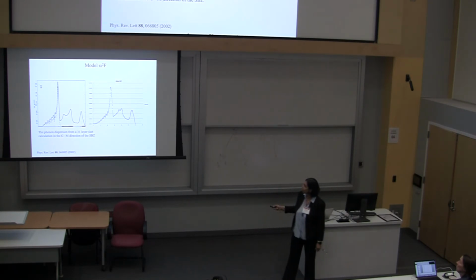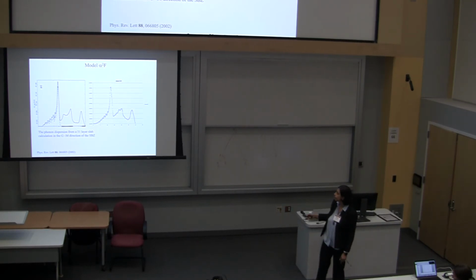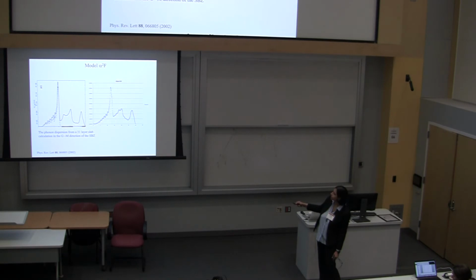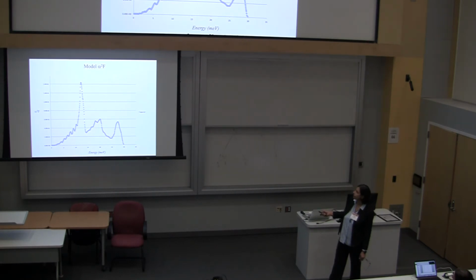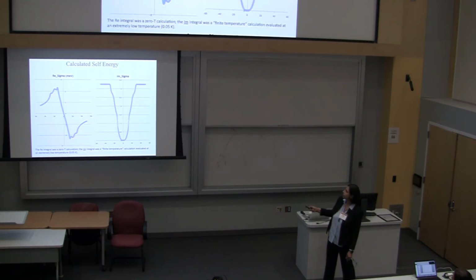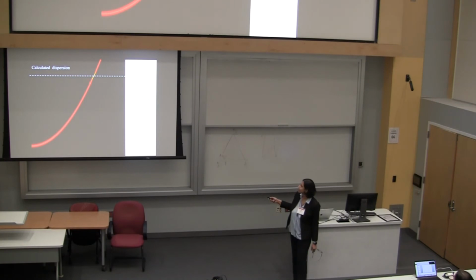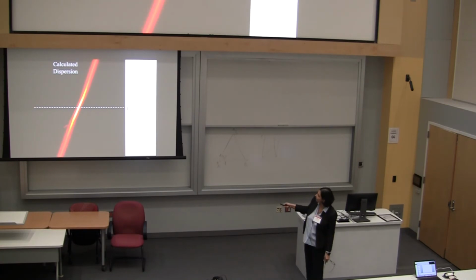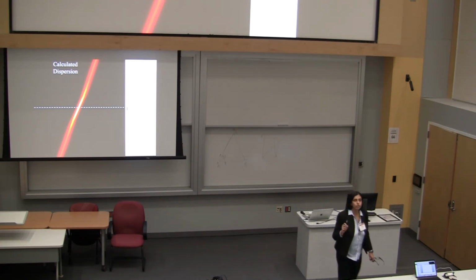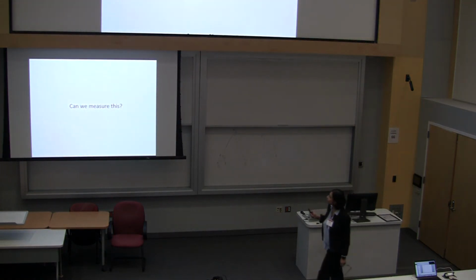So here's a model alpha squared F. This was actually done using a calculation in 2002 for copper, right? So this is what your phonon density of states looks like, and this is what we used as an input. By just using this alpha squared F as an input, we got the real part of the self energy and the imaginary part of the self energy. That's what they look like. And now we can calculate the dispersion. Everything looks the same except something has changed near the Fermi energy. And there you go, you can get this slight kink. This is the calculated dispersion specifically for copper, because we know the band structure of copper really, really well.